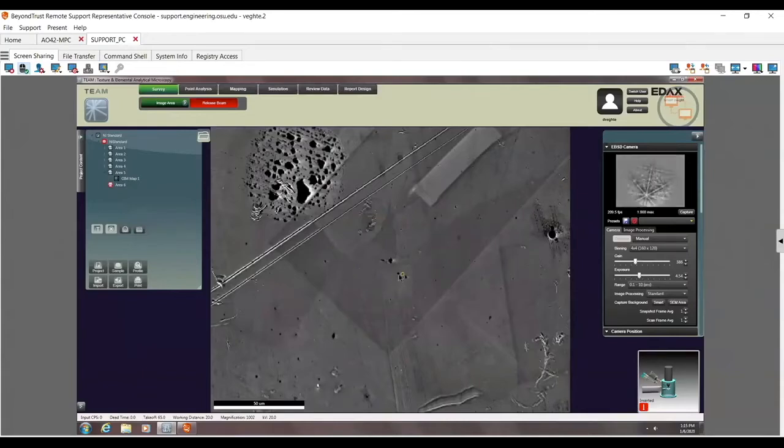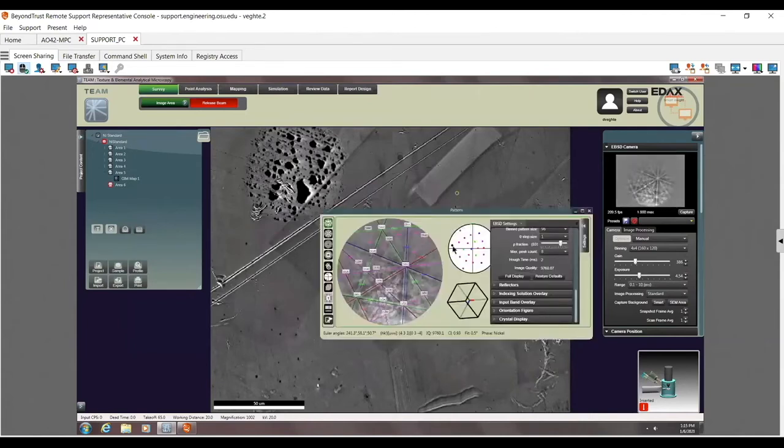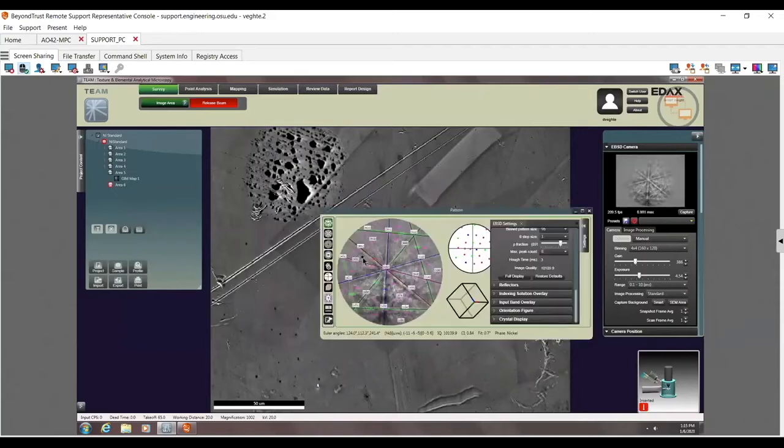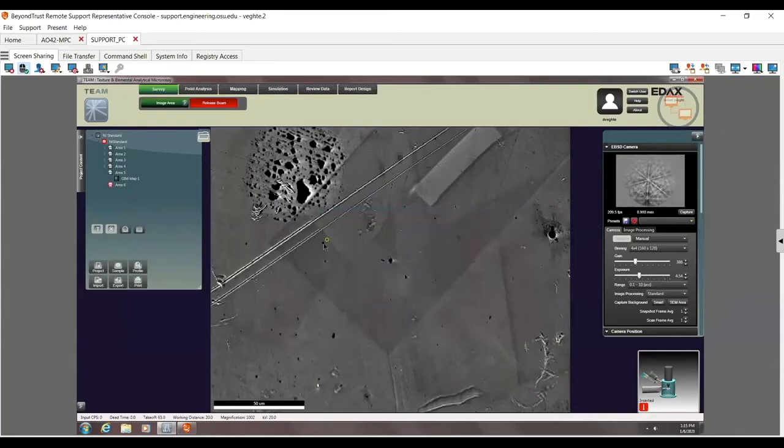So usually if you're doing a map, I do what I call a flick test. I go here in the middle, and I flick it up towards a corner. Say, okay, yep, good pattern. Do it again. And you say, oh, good pattern. Now, again, this is a real world sample. Again, it looks like somebody sneezed on it.